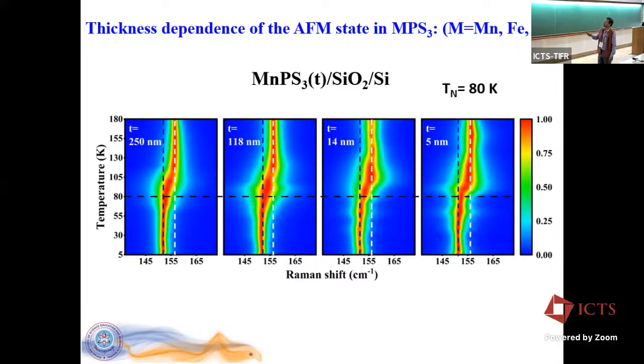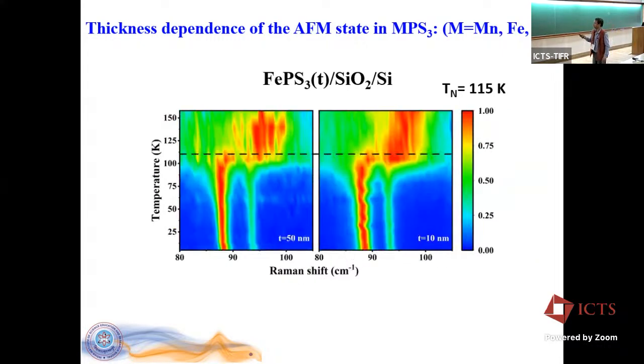So this shows that no matter how thick or thin a flake of MnPS3, FePS3, or NiPS3 we take, the antiferromagnetic ordering, or the magnetism, is extremely robust. It doesn't change at all, okay? At least not to the level where we can really perceive. So here the Raman data shows, starting from about 250 nanometer thick, okay, very thick, then about 100 something, about 14 nanometer, 5 nanometer, you can see this transition is right at that same temperature, okay? And this has again been established by some people in the literature.